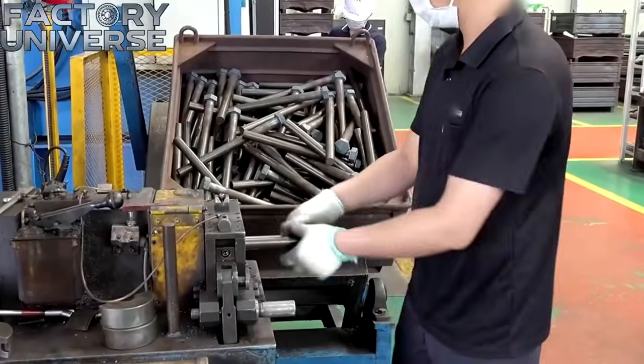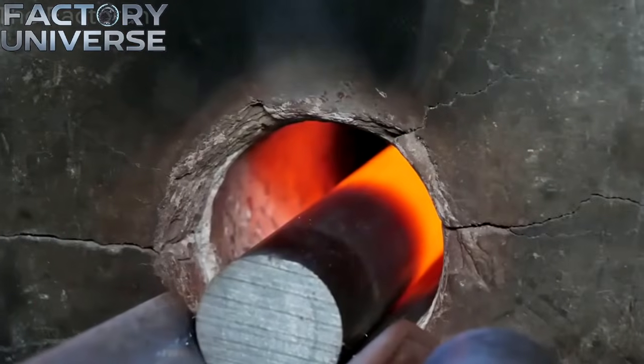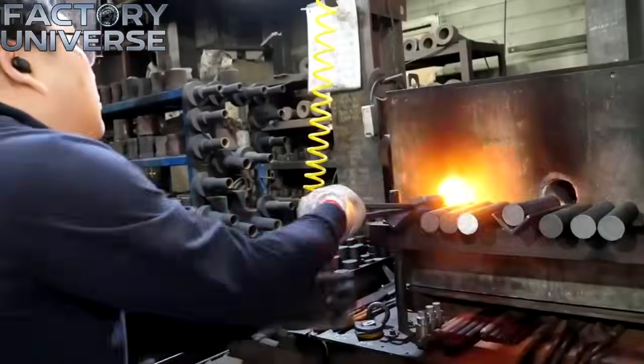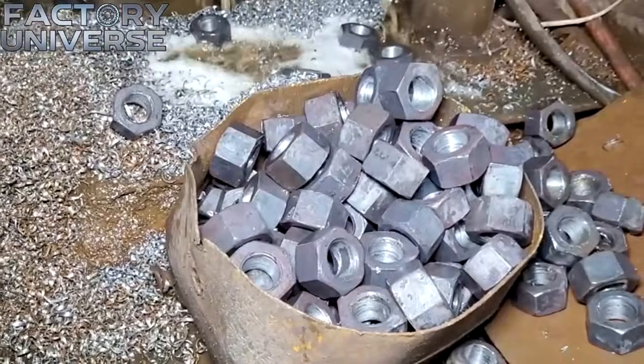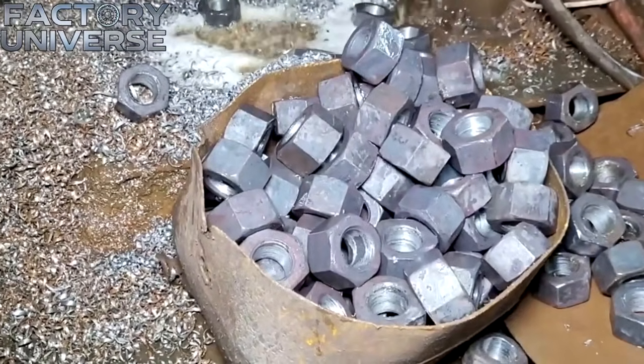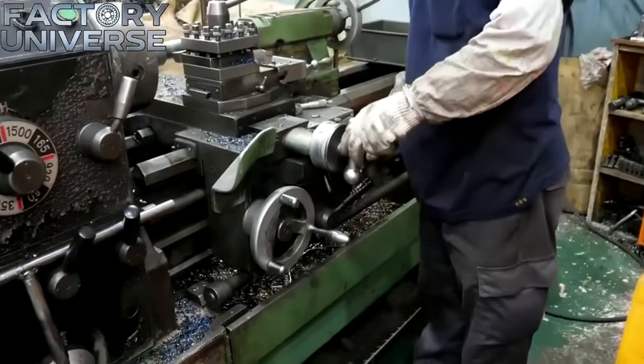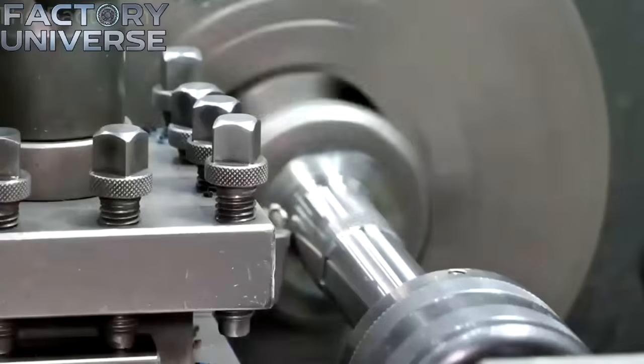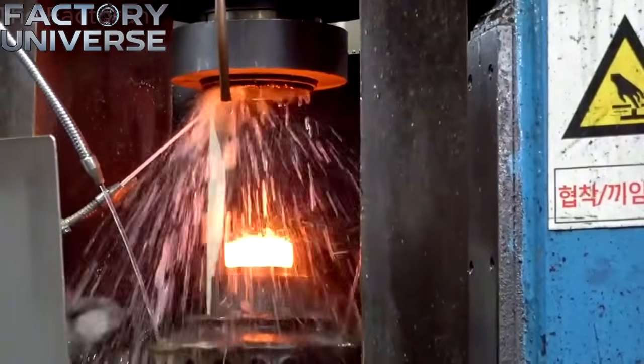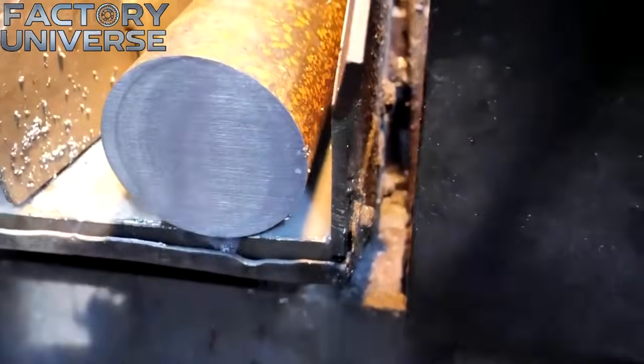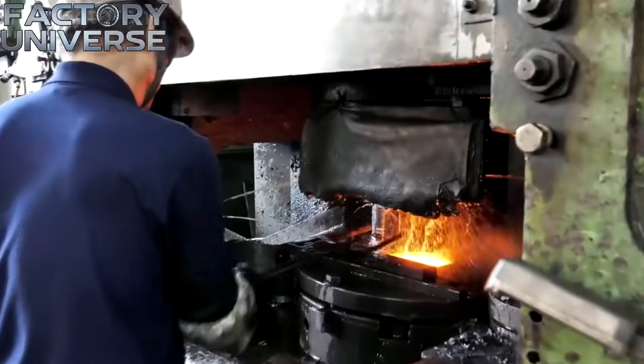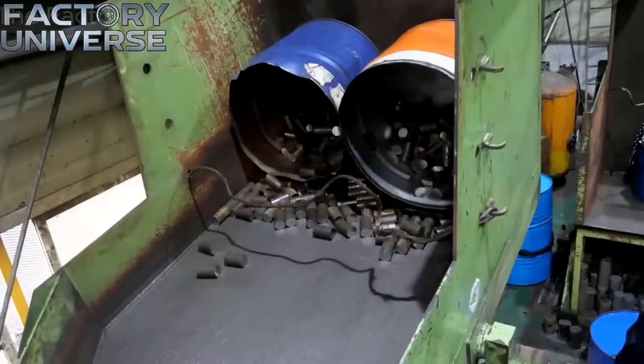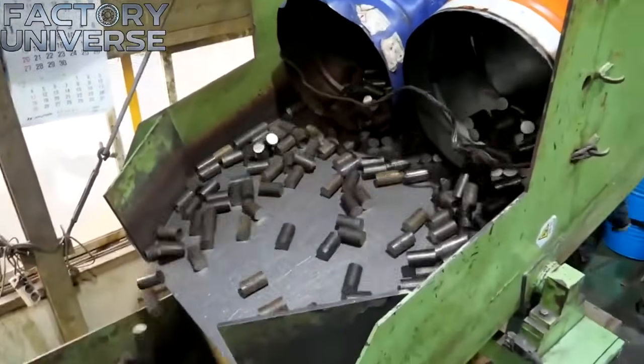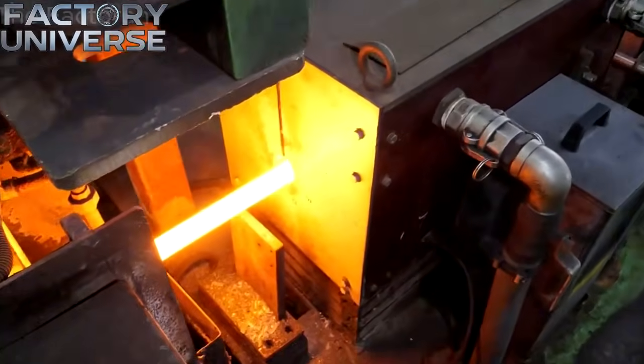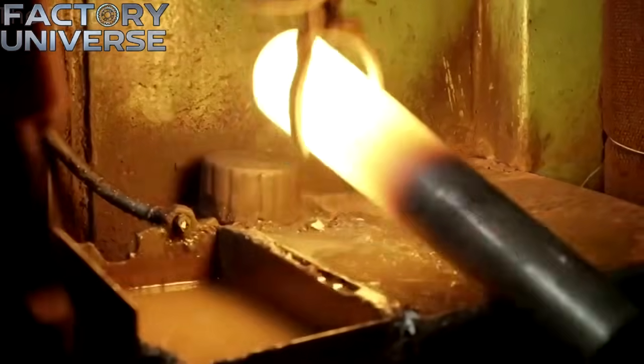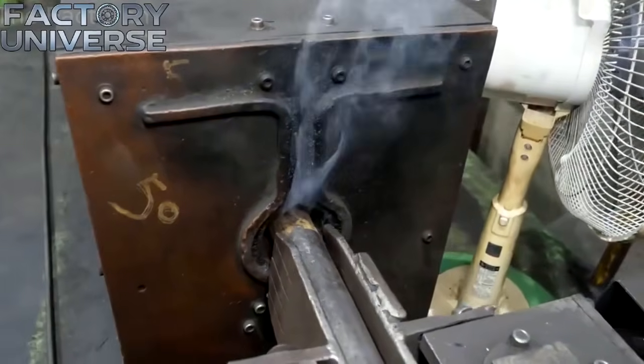2,100 degrees Fahrenheit. This is the peak temperature required to prepare the steel for the next stage of transformation. While both components move to the heating phase, the application of thermal energy differs fundamentally between the two. For nuts, the entire cylindrical billet enters a continuous furnace to undergo uniform heating across its entire volume. This full-body thermal treatment brings the metal to a completely plastic and homogeneous state, allowing it to flow evenly within the forging die. It is visible how the glowing steel reaches a state where a solid hexagonal body can be formed before any internal drilling or threading occurs.